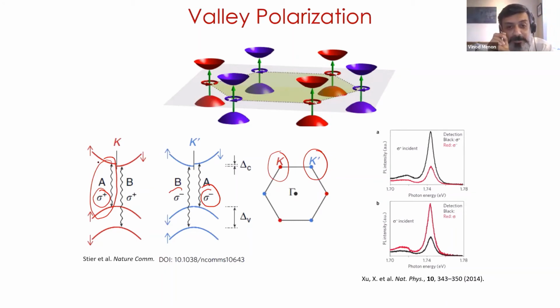The result is that when I come with right-handed circularly polarized light, or sigma plus light, what I get out, or the photoluminescence that comes out of the system, is also sigma plus. So here is data from this paper here. They show that if you come with sigma plus light, you get mostly sigma plus emission. You come with sigma minus, you get more sigma minus. So this property is called valley polarization. And because of this property, people also refer to this valley degree of freedom as a valley pseudo spin. So it's like a spin property, and so it's called the valley pseudo spin.